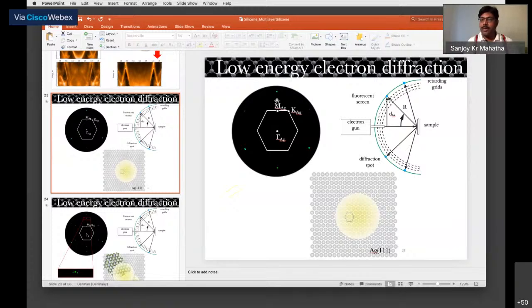And from the spot profile analysis, that means by seeing the spot intensity with respect to background, one can also say if you have any dirt on top or not, and if your surface is well ordered or not. If you have any kind of stepped surface, your LEED pattern will be a little bit different. And when you put something on top, as I showed, you get another LEED spot, and from there you can calculate the lattice parameter of the overlayer with respect to your substrate. So these are the quantitative analyses one can do. But the error bar will be a little higher than other techniques. If you really want to determine the structural parameters, then I would do X-ray diffraction, not LEED. LEED is just to know if my surface is good, if I have what I wanted on the surface, and also to align the sample along a particular symmetry direction.